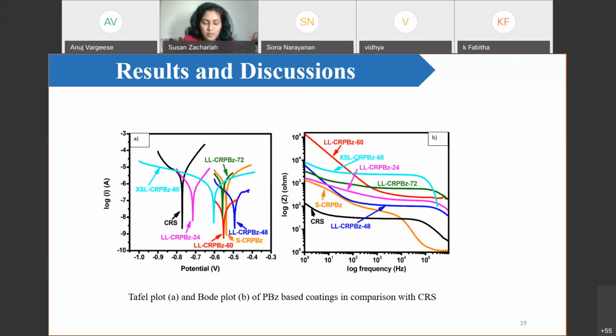In the first picture, we have used different times like 24 hours, 48 hours, 60 hours, 72 hours of pre-treatment before keeping the PDMS negative template. We found the best sample which shows the maximum protection efficiency is the 60-hour pre-treated lotus leaf based cross-linked PBz, and the Bode plot also successfully showed the same results: lotus leaf based cross-linked PBz for 60 hours gave the best result.